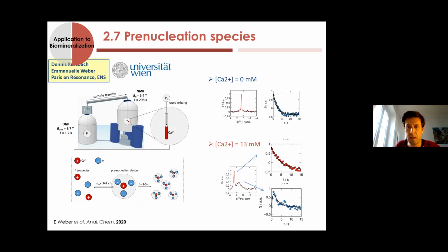That's very interesting because at the very first step, we are able to see not only one resonance corresponding to the free phosphate, but two resonances, one corresponding to the free phosphate and the other corresponding to the prenucleation species.